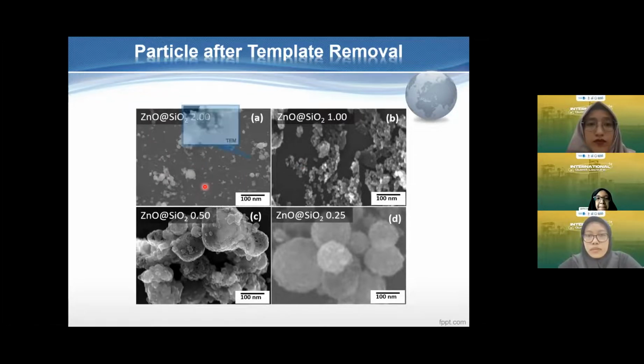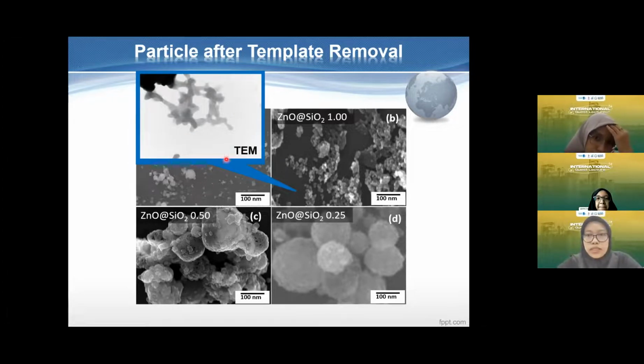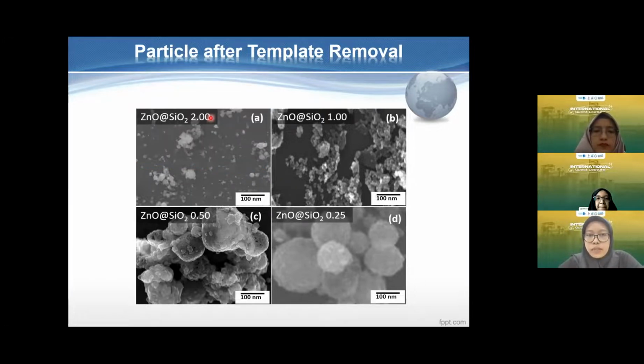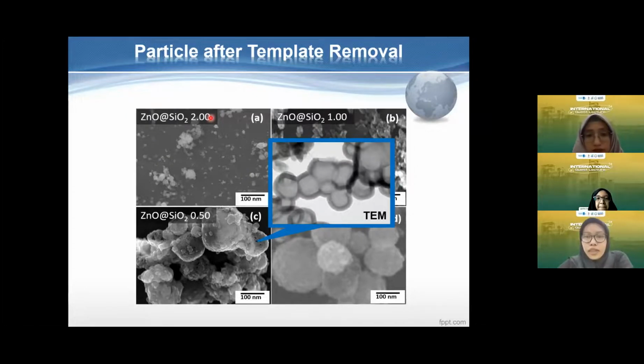So maybe from the clear one using the TEM, there is no big particle size, so there is no zinc oxide here, only the silica particles, because this particle is more transparent than zinc oxide particles. This one, if we compare with the previous slide, before the zinc oxide particle was removed, and after we remove the particles, there is no black part here, because the zinc oxide is already removed from the particles. So here we can obtain the hollow silica particles. So this is only the silica particles.